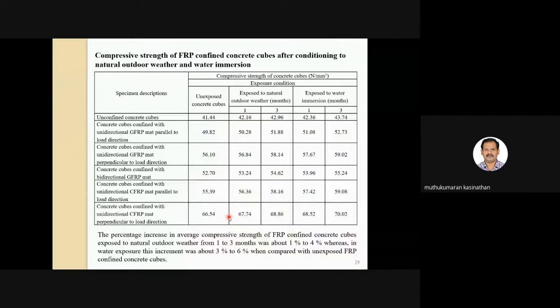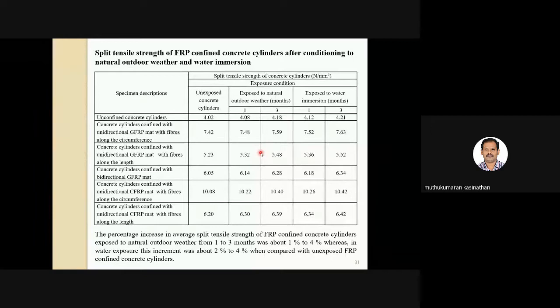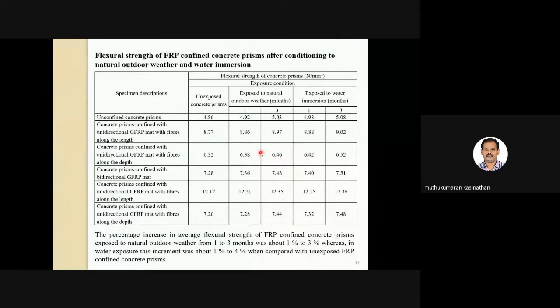And in fact, when the specimen is immersed in water, as you all know, initially the strong concrete specimen will gain a little bit of strength because of the exothermic process. We also noticed a slight increase in strength, but our ultimate idea is to check whether there will be any issue related to debonding. We noticed that no more debonding happened even after 3 months of water immersion. That is a good sign that this material can be used underwater as well. We have conducted all the tests, and nowhere was strength reduction noticed.